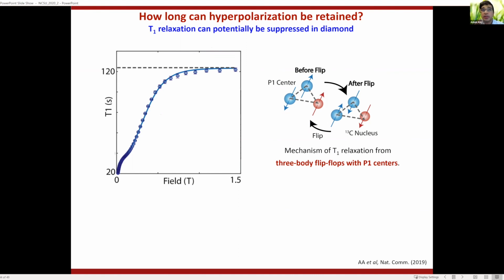Yeah, I didn't mean you can stop it. So by operating the P1 centers, you can reduce the effective polarization or the rate of polarization. But indeed, the NV is seeding the polarization. So if you switch off the NV, you don't shine light on it anymore, then you get a rate constant which is just spin diffusion related, and this goes in a few seconds.